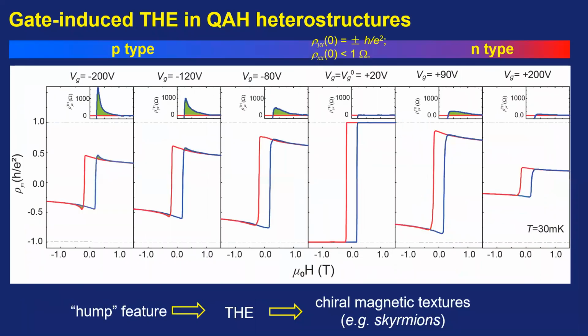So let me show you the gate dependence of this kind of sample. When we tune the gate to the charge neutral point, almost 20 volts, we can see it shows a very good quantum anomalous Hall state, and the longitudinal resistance is below 1 ohm. So this is the best quantum anomalous Hall state. When you apply some minus gate voltage, at minus 80 volts, we introduce some hole carriers in the sample. There is a feature that comes out. There is a hump showing in this hysteresis loop.